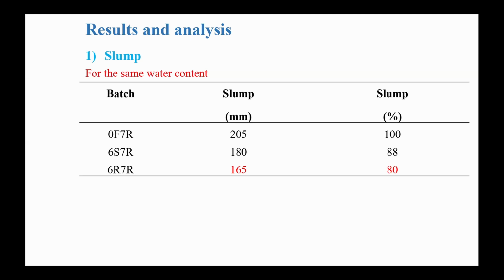It is worthy to mention that in the plain concrete, in all 3 batches of the concrete, there was 75% replacement. We replaced 75% of the natural aggregates with 75% of the recycled concrete aggregates. So here the 7R represents the recycled 75% replaced natural aggregates, and 0 represents 0% of the fiber, that is the plain concrete.